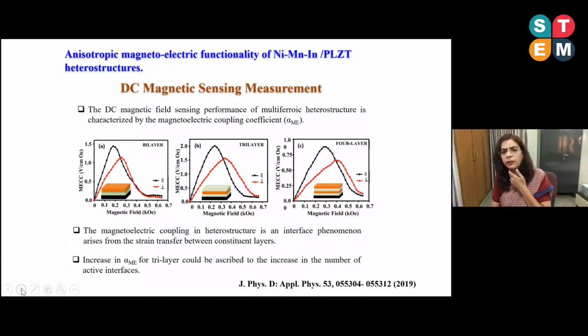The reason we attribute is that when we go to the tri-layer configuration, we were able to get better magneto-electric coupling, which is an interface phenomenon arising from strain transfer. Strain transfer was better in the tri-layer case compared to the bilayer. But as we go to the 4-layer, the number of layers increases and the leakage current density also increases, and maybe our interface was not so pure. Because of that, there was a reduction in the value of alpha in this case.